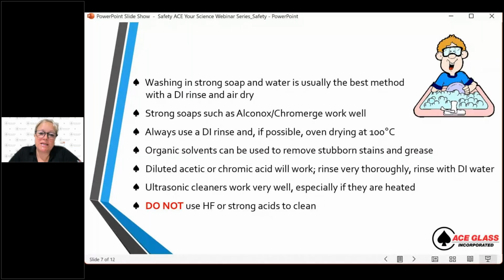You can use diluted acid, such as acetic acid or chromic acid, but then always make sure to rinse with DI water. Ultrasonic cleaners can work well. However, they do have their limitations because the ultrasonic energy actually can cause your glassware to go blind. Do not ever use a strong acid such as HF in your glassware. It will straight up dissolve it, and then we have bigger issues to deal with.